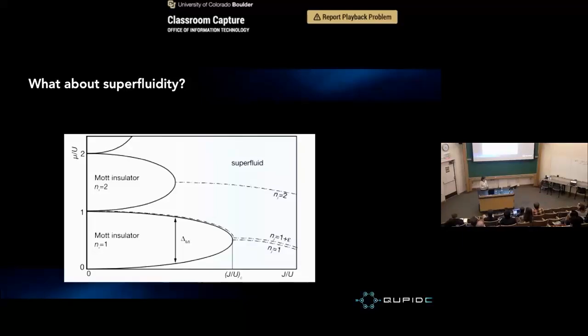Anyway, so then the question is, okay, we know now we can see this Mott insulator phase. What about superfluidity? Can we also get to that phase? It turns out it's actually very hard. The reason is that in the Moiré TMDs, in order to get to U smaller than J, you could get that, but then your disorder becomes much more important, and your disorder kind of dictates your physics.